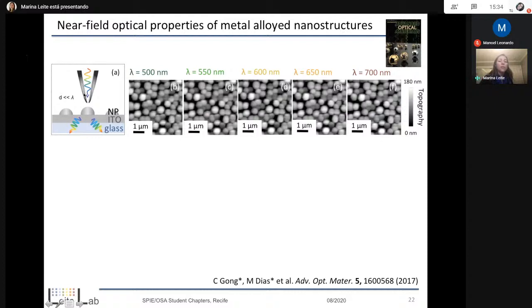We basically use a probe, such as an atomic force microscope probe. In this case, the probes are hollow. We pass light through these probes, and we can select the wavelength. Then we raster scan the surface of our sample, much like a record player. You might be too young to have seen a record player in your life, but that's basically what you're seeing. And then what we do, we acquire information regarding the morphology of the particles, and simultaneously, we also collect light that has been transmitted in this case. We use an objective lens here underneath that is not represented in this schematic. So basically, we can spatially and spectrally resolve the near-field optical response of these nanoparticles.